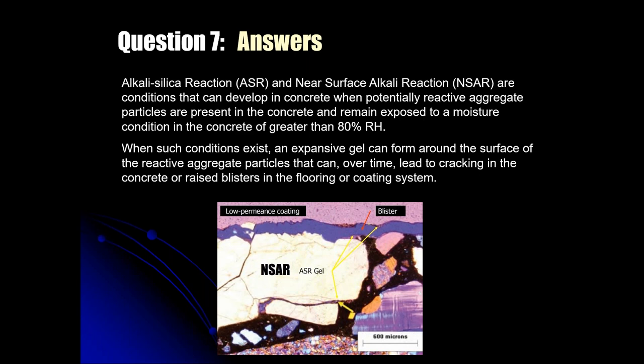Okay, if the relative humidity in the concrete is 80% or higher, it provides the fuel, if you will, for an alkali condition to develop and exist, and for these particles to be affected. Now, with a classic ASR condition, with a coarse aggregate particle, when ASR begins to develop, an expansive gel forms on the surface or the periphery of the aggregate particle, and that gel is like a crystal of ice. It can actually create a force great enough to fracture the concrete.